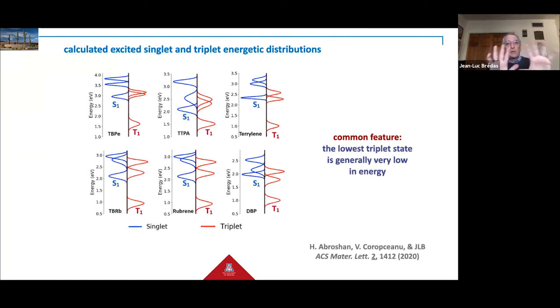And one first thing that Hadi found out is that in those typical fluorescent emitters, when looking at the energy distribution of the triplet state and the singlet state in the emissive layer, he found that the lowest triplet is very low in energy with respect to the lowest singlet. And that's the case across the 6 fluorescent emitters that he investigated.